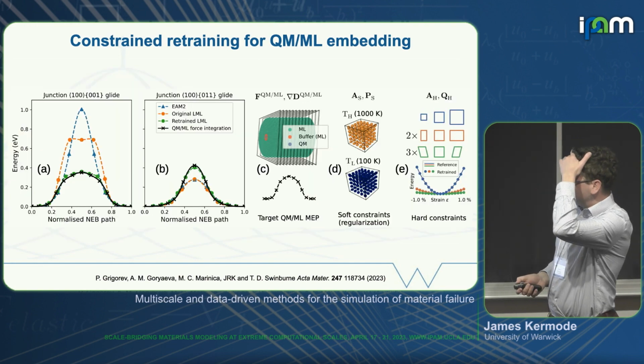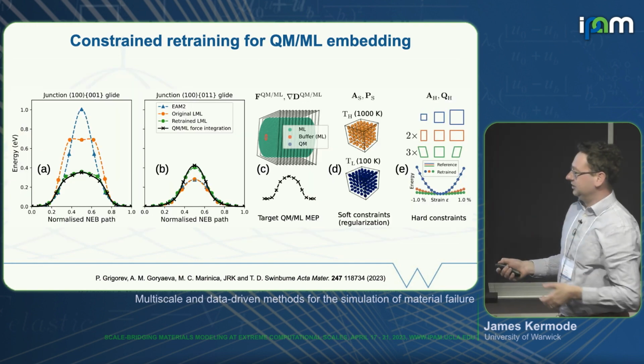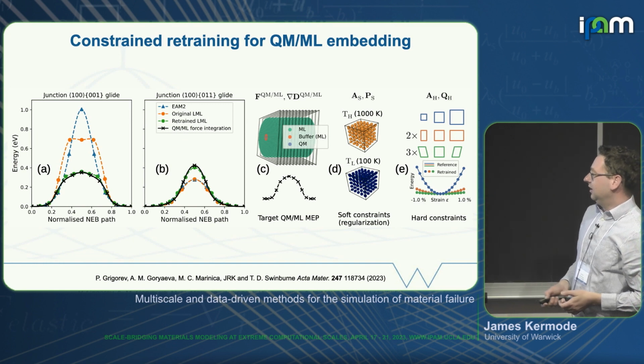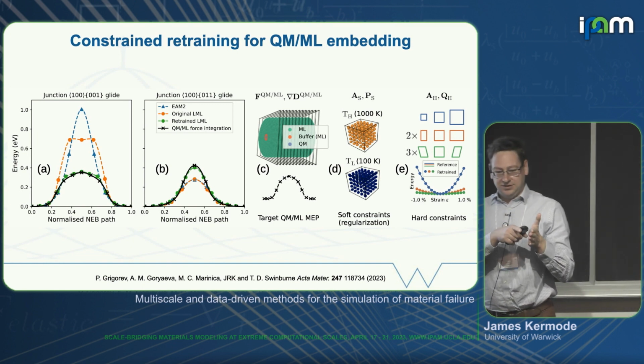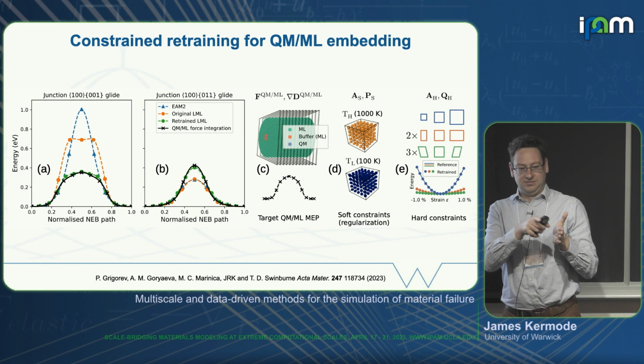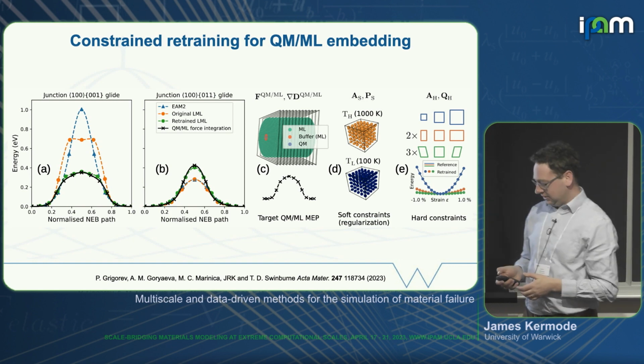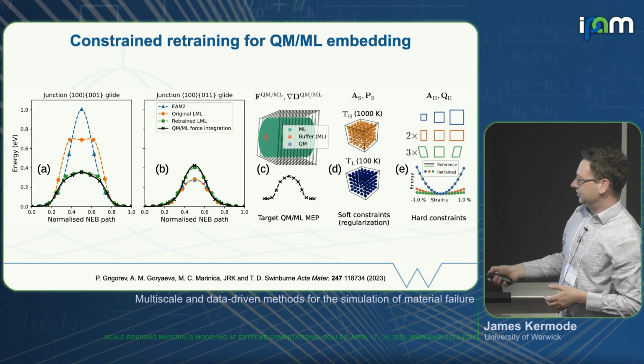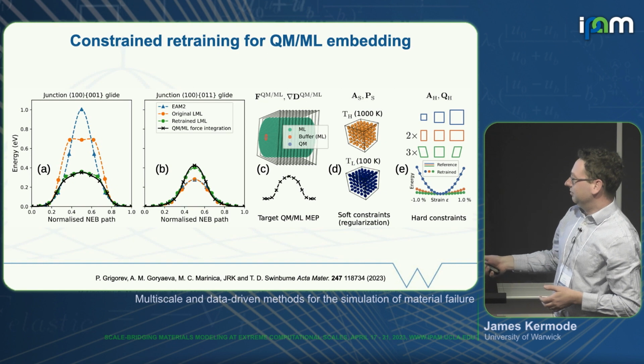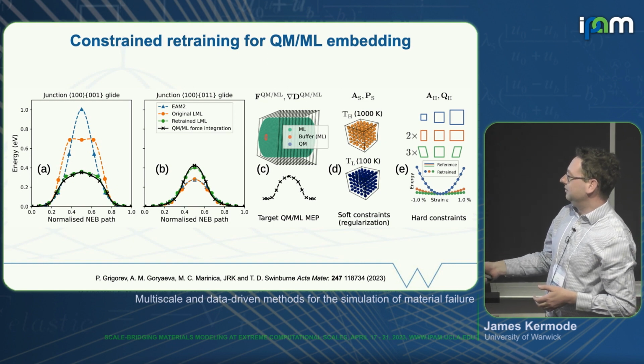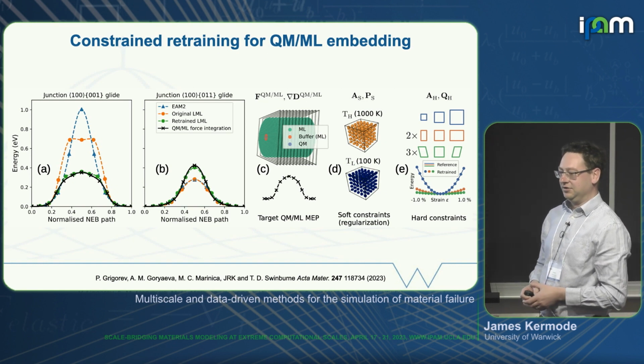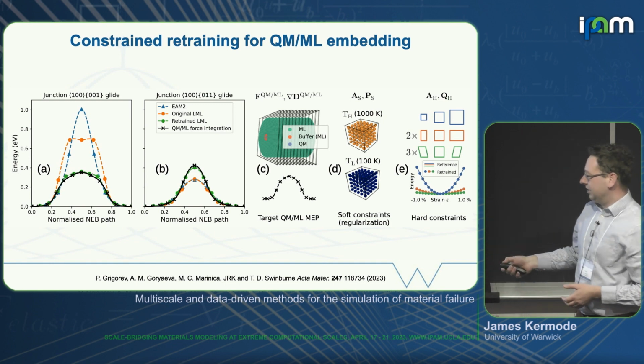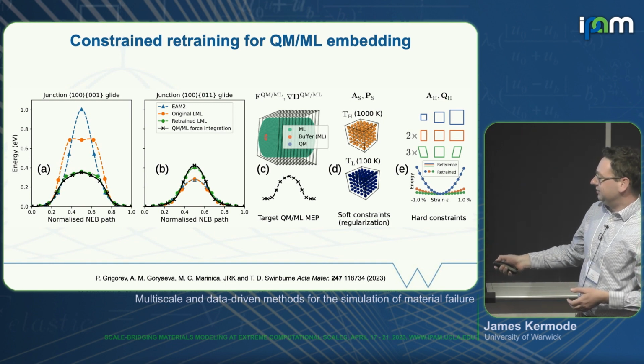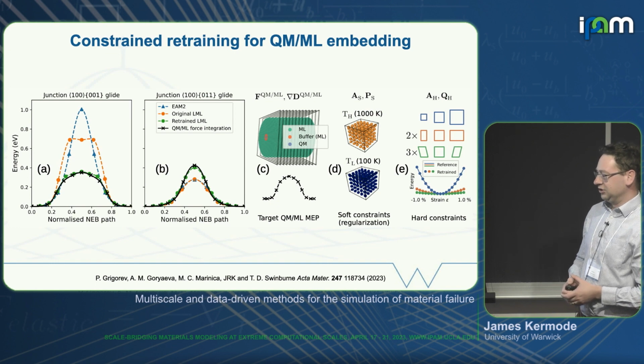How does it work? Well, we do some reference calculations with the existing method, and we look at the glide barriers for dislocation motion. So we work out how easy it is for dislocations to move from one side to the next. That gives us a bunch of reference configurations, shown in black here. Originally, the potential on its own is not able to describe those environments adequately, but what we can do is take those black minimum energy paths and use them to update the potential parameters.